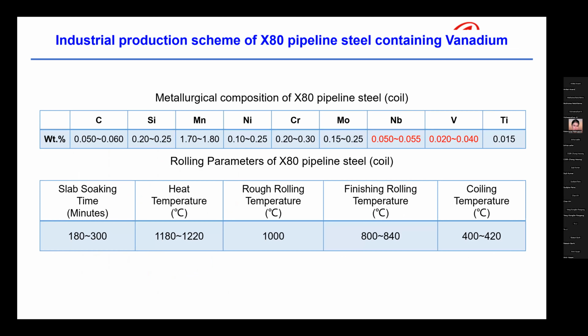To this step, lab research is completed, and based on the results, we have designed an industrial production scheme of X80 pipeline steel containing vanadium. The main change is in the metallurgical composition. Niobium is reduced to 0.05% from 0.08%, and vanadium is increased to 0.03%. Rolling parameters don't change a lot.